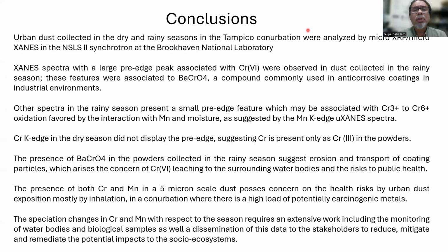So to conclude this presentation, we analyzed some urban dust powder samples collected in the rainy season and in the dry season in the Tampico conurbation. As we mentioned, it's a conurbation with about 1 million inhabitants, with a lot of industry. We observed some particles where barium chromate was suspected that would come from anti-corrosive coatings in industrial environments. Other samples during the rainy season present peaks associated with chromium-6, while samples collected in the dry season do not present almost any evidence of chromium-6, which, coupled with the variety of oxidation states we observed in manganese, indicates a large interaction between the moisture and the metals present in the dust.